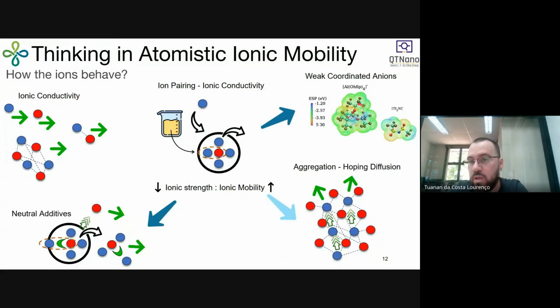So we can use weakly coordinated anions to decrease this binding energy here and increase the exchange between the ions within the solvation shell. We can also use neutral additives, such as water or organic solvents, in which we are breaking this interaction here because we have the solvation of the neutral molecule and the anion, so improving ionic conductivity. Or we can also use aggregation. So we are going to have a lot of ions together. This large number of interactions between cations and anions decreases the binding energy between them, and we can see some jumpings in which the cation can move across different solvation shells. So this is one way to think about ionic conductivity and how to control it.